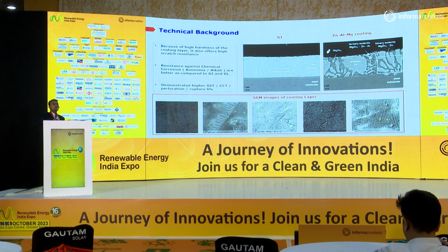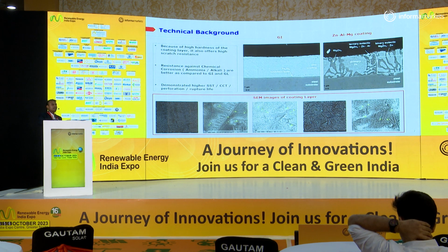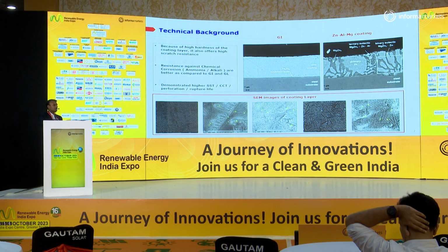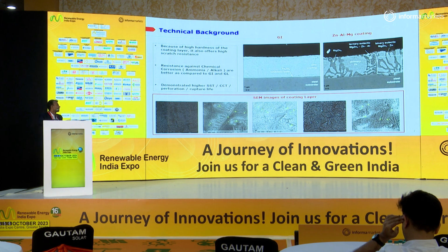So this product was developed at lab scale using a physical simulator, where we experimented with different compositions and engineered the coating behavior to optimize its performance. Exhaustive characterization and metallographic studies were conducted, and this product now offers high scratch resistance, which is because of its relatively high micro hardness, and high resistance to chemical corrosion, like against ammonia and alkali, as compared to GI and GL, and has demonstrated high SST and CCT life and resistance to corrosion when it comes to perforation and rupture life.